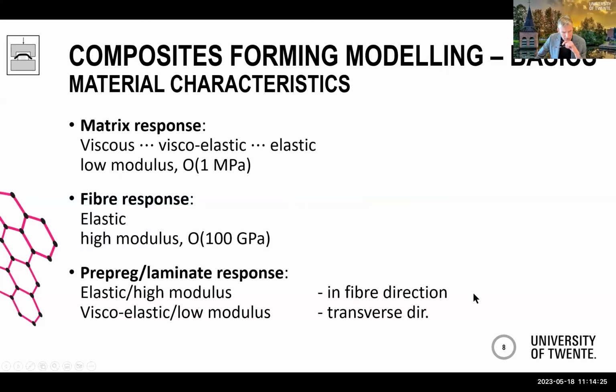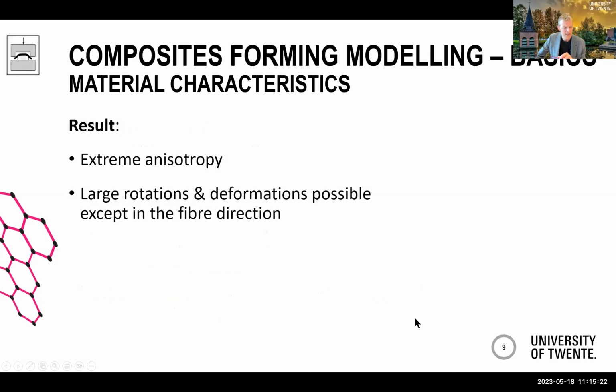If we look a bit closer at the material we're trying to describe, remember we're talking about primarily thermoplastic matrix composites in molten condition. The matrix is obviously in a viscoelastic state, and if we were to assign a modulus to that, it would be typically in a rubbery region, so low, let's say 1 megapascal order of magnitude. Whereas the fibers obviously remain in their elastic state, high modulus, let's say order of magnitude 100 gigapascals. So combining that in a prepreg or a laminate, this laminate has a high modulus in fiber direction and a pretty low modulus for loading in any transverse direction. So that gives rise to what I would call extreme anisotropy, 5 decades of difference in moduli.